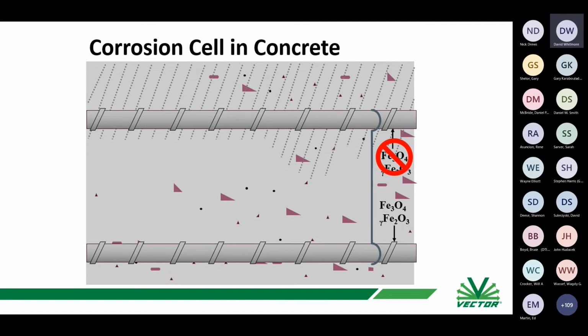Okay, until that happens, you won't see any signs of corrosion. When that happens, corrosion is an electrochemical process, so the iron in the steel starts to dissolve, giving off electrons. If there's chlorides there, that tends to act as an accelerant. And the corroding areas we call an anode.